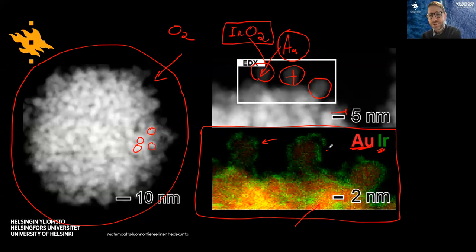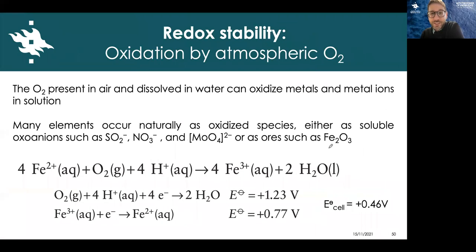So by this approach, by using visible light, for example, we were able to go beyond the performance of iridium oxide. So we improved the activity towards the oxygen evolution reaction beyond the benchmark material, which is iridium oxide. So we could make iridium oxide an even better catalyst for the oxygen evolution reaction under visible light, which opens up the possibility of using sunlight in the future. This is the overarching goal for the future: to use sunlight as a sustainable energy input and some catalytic materials to enable both the hydrogen evolution reaction and the oxygen evolution reaction, which is particularly challenging as I described in the previous slide.